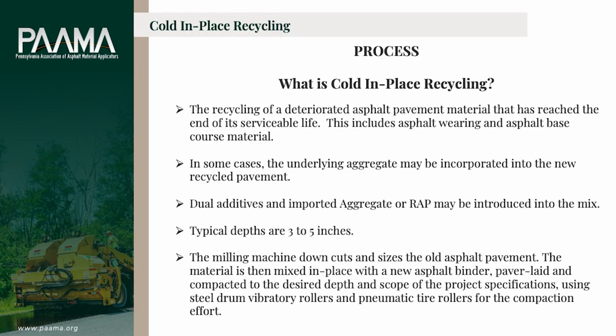Dual additives. We use a dual additive today. It used to be that we could only use an emulsified asphalt, but we now can add aggregates to it. We can add Portland cement, and there are other additives we can use. I like to see an emulsified asphalt with 1% Portland cement, and we'll talk about that a little later. Typical depths, 3 to 5 inches compacted.